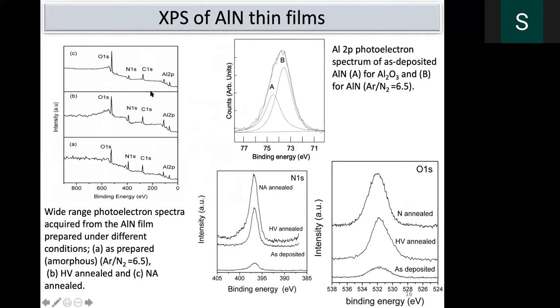But when you see the broad spectrum, that wide, all the elements are present, but you cannot understand it very clearly. But when you see the aluminum and the nitrogen, particularly the oxygen peak, in the as-deposited case, yes, of course, there is a small amount, but when you anneal it in a nitrogen atmosphere, this alumina formation is suppressed. That's what these peaks show when they shift towards the left, particularly in the nitrogen case, and in the oxygen case also. So this is very important to understand.